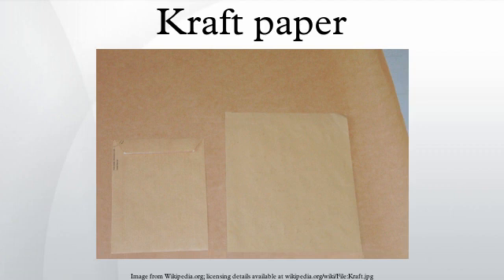Pulp produced by the Kraft process is stronger than that made by other pulping processes. Acidic sulfate processes degrade cellulose more, leading to weaker fibers, and mechanical pulping processes leave most of the lignin with the fibers, whereas Kraft pulping removes most of the lignin present originally in the wood. Low lignin is important to the resulting strength of the paper, as the hydrophobic nature of lignin interferes with the formation of the hydrogen bonds between cellulose and the fibers.